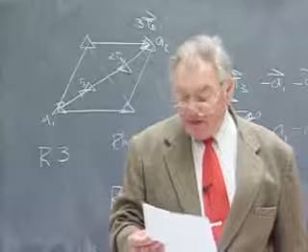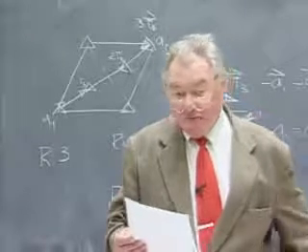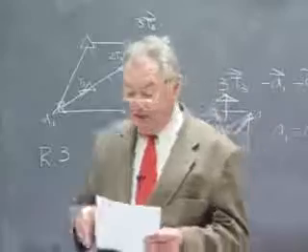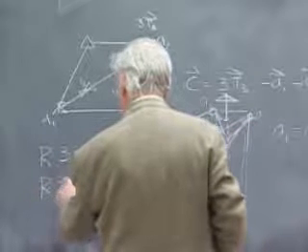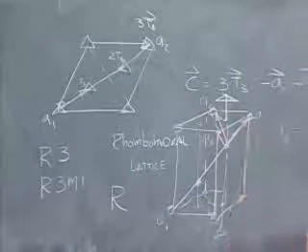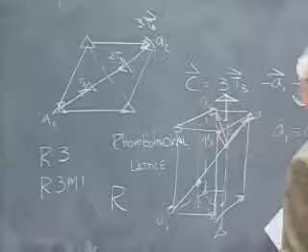For P3m1, I have symmetry 3m at both the origin lattice point and in the center of these two triangles. So for P3m1, in addition to a threefold axis, I could put in 3m1, stack up plane group P3m1. But I cannot do this for P31m.